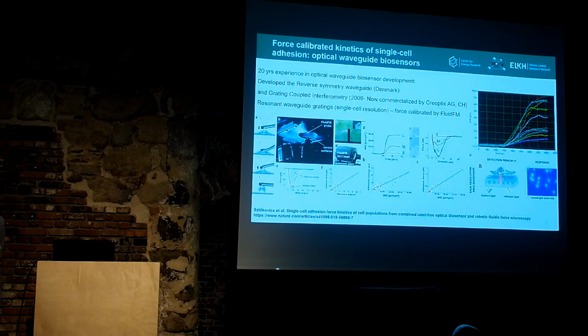And then we came up with an idea: let's combine these two techniques. We built a system where we perform the measurement on the optical waveguide sensor chip and measure the kinetic curves of the adhesion events. After that, we remove the optical waveguide and put it underneath the fluidic force microscopy and measure the force distance curves by this mechanical technique on exactly the same cells.